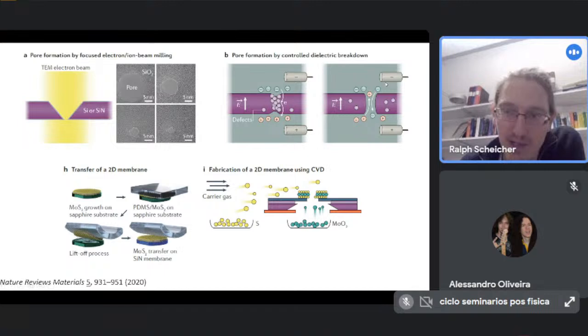And you see this in this experiment by monitoring the ionic current. In the beginning, when it's not yet broken down, the ionic current will be essentially zero or very, very small. And then when it's broken down, you suddenly see an increase in the ionic current, and then you can quickly, through some electrical circuit, switch it off. And in that way, you can actually, in quite a controlled way, create a nanopore. So this has been done in practice also.